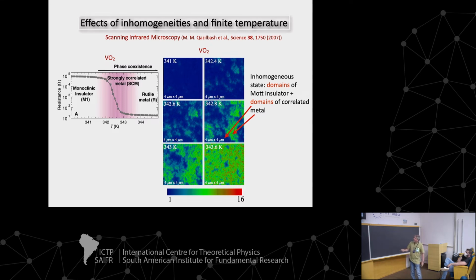So this is basically the conductivity. This is low conductivity, this is large conductivity. And you see that there are regions which are more red and regions which are more blue. So you have domains of Mott insulators coexisting with domains of metals. And of course, there's going to be interfaces between them.